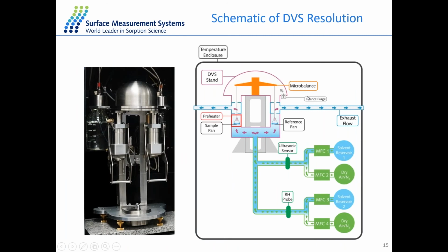Here I just want to use an example from the DVS Resolution, which can perform the sorption of both moisture and organic vapor, as well as the competitive sorption of two different components. In the middle here, we have the microbalance with a resolution of 0.1 microgram. It's connected to both the sample pan and the reference pan.